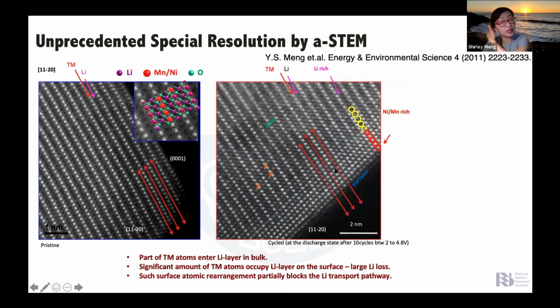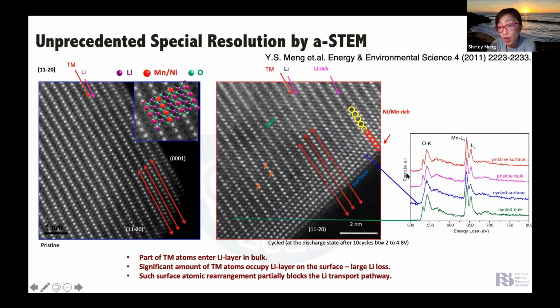So this was the first example we demonstrated that for cathode materials, we have to find ways to protect the surface, especially if the cathode is exposed to high voltage. At high voltage, we can have oxygen loss, and the transition metals, nickel and manganese, will migrate to the lithium layer, causing serious impedance growth. This is one of the early examples where we showed that atomic resolution imaging methods can help engineers and scientists pinpoint where the problem is and how to resolve it.